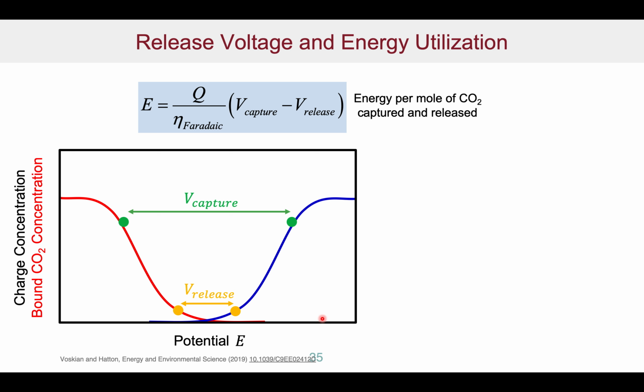Now, the energetics, the release voltage, are of course important. The energy is given by the charge transfer divided by the Faradaic efficiency, times the difference between the capture and the release voltages. As we talked about before, this is the bound CO2 concentration, and these are the capture and release voltages in the system. If we get this release voltage, we have that amount of CO2 released. If we have a smaller delta V, in this particular case, we only have a smaller amount of CO2 released, but the energetics are also going to be smaller.